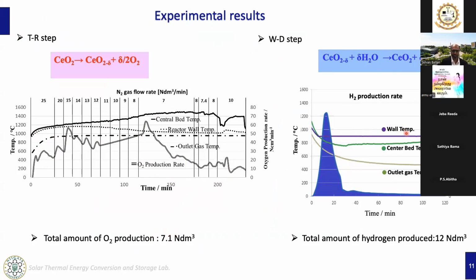And during the second step, as you can see, other details like the wall temperature, central bed temperature, and the outlet gas temperature. And this profile shows the hydrogen production rate. So at the end of the second step, we produce around 12 liters of hydrogen. So using 8 kilograms of cerium oxide particles, we produced around 12 liters of hydrogen.